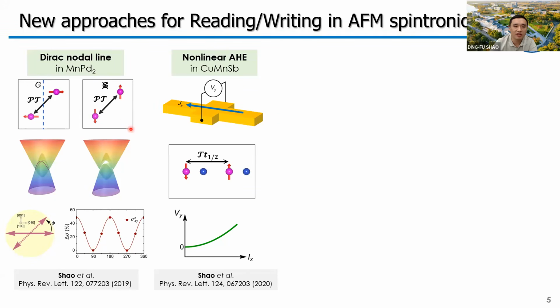For example, we found in some antiferromagnetic metals near the Fermi level, there might be a Dirac nodal line protected by a symmetry. The Néel vector rotation can control this symmetry, leading to the gap opening and closing, switching between the gap opening and gap closing states along this Dirac nodal line. And this will generate a sizable change of the spin Hall effect.